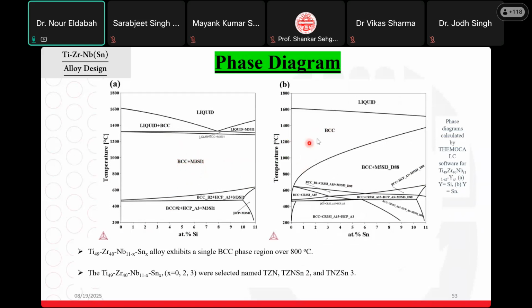However, for the tin containing alloy, if we stabilize the BCC beta phase around 1000 degrees Celsius, we can add up to 3 atomic percent of tin to our alloy. So in both cases, we will not depend on the silicon because it is not suitable for our case, and we will use tin.